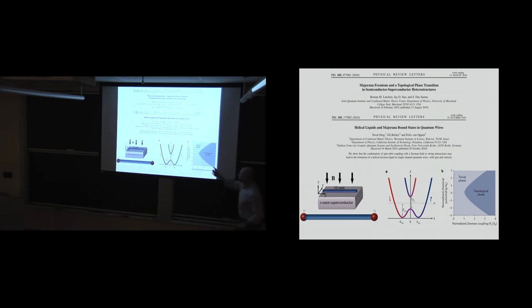The magnetic field has to be sufficiently large that you enter this so-called topological phase. This is the one in which this separated Majorana at the ends appears as the ground state of the system. And it requires a magnetic field. And look, it's a lot of magnetic field. It's a magnetic field in which the Zeeman energy exceeds the superconducting gap. This is bigger than one. That's normally the criterion for killing superconductivity.